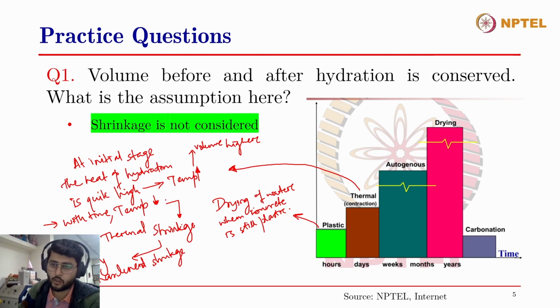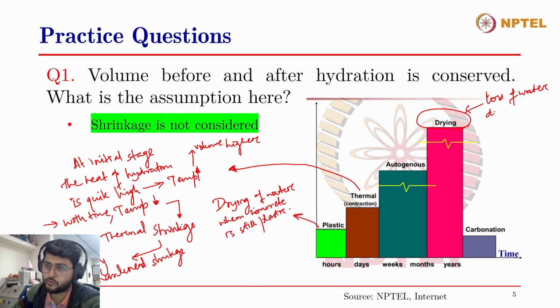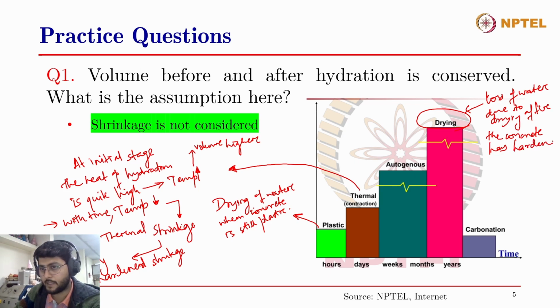And then, as we discussed, autogenous shrinkage can start from the fresh state, and the autogenous shrinkage after set can continue for several months. And then there is drying shrinkage. Drying shrinkage is again loss of water due to drying after the concrete has hardened. Again, this also will induce cracking in the concrete.